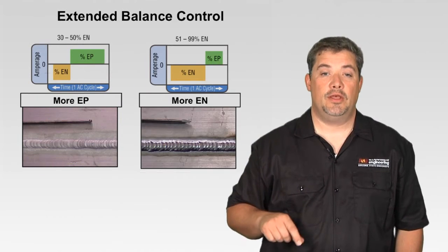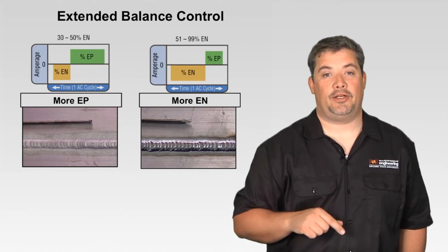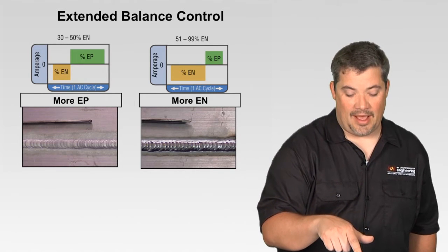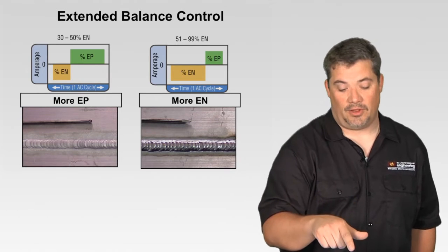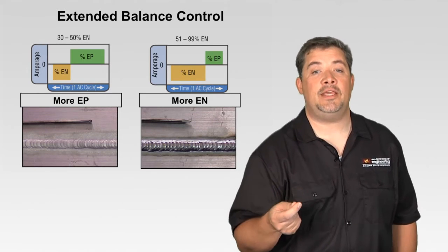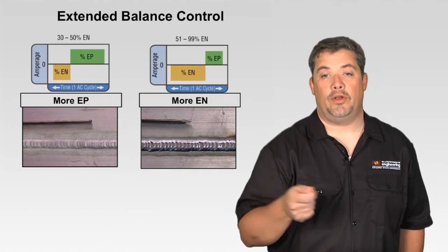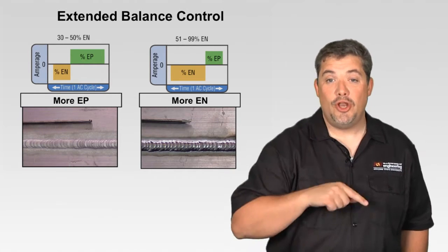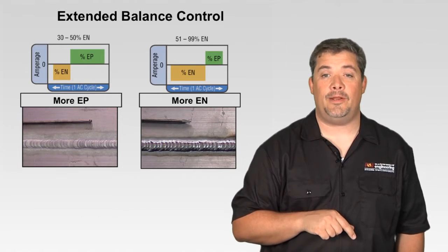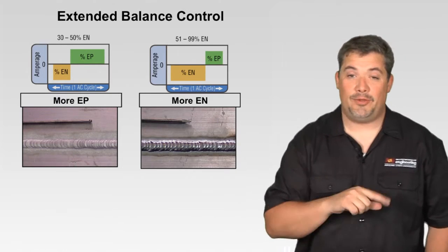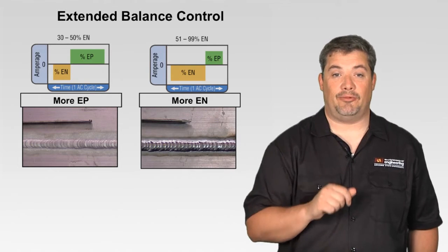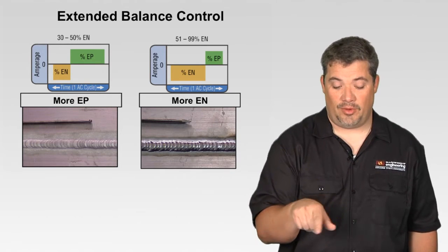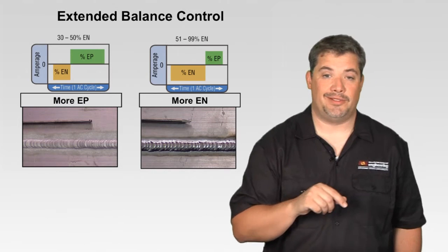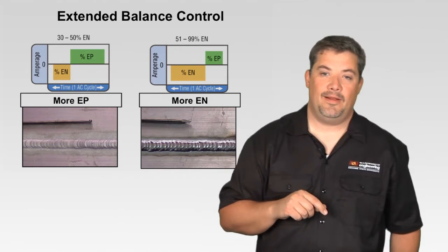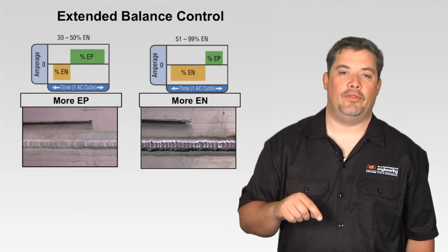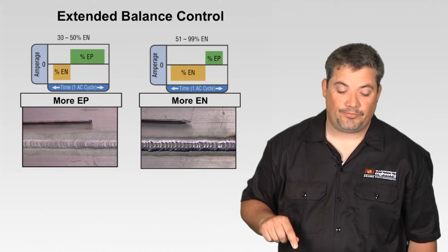a conventional machine. So here you can see in the illustrations with a lot of electrode positive, I get a lot of etching going on. Even onto the surface of my bead, I have a large ball in that tungsten, so there was a lot of heat going on the tungsten. When I went to electrode negative, you can see there's almost no etching zone, and that tungsten is almost sharp like a needle. So that gives me significant control between these two. The beads might look the same size, but they're really not. Probably both are the same 3/32 diameter tungstens, so if you really started scaling these images, you'd probably see that bead is certainly more narrow on the electrode negative one than it was with the electrode positive image.